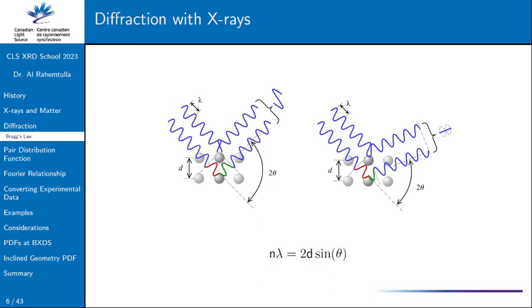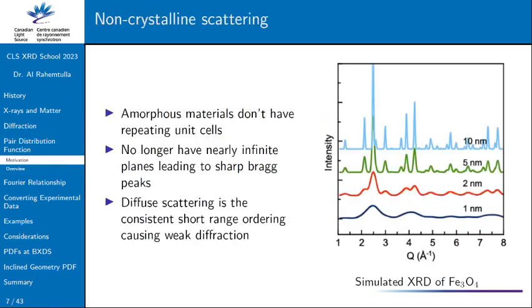And we've seen already how powerful Bragg diffraction can be, but in some cases it doesn't always work. Besides the obvious of something with no long range order, so liquids and amorphous materials, nanomaterials are another case. As we start getting finite sizes, there's going to be peak broadening that occurs because we no longer can rely on the infinite, or nearly infinite, plane of atoms that gives us that nice constructive interference. So as that happens, we get more and more broadening due to that finite size limit. And as we get smaller and smaller, that also means that long range order starts diminishing away.